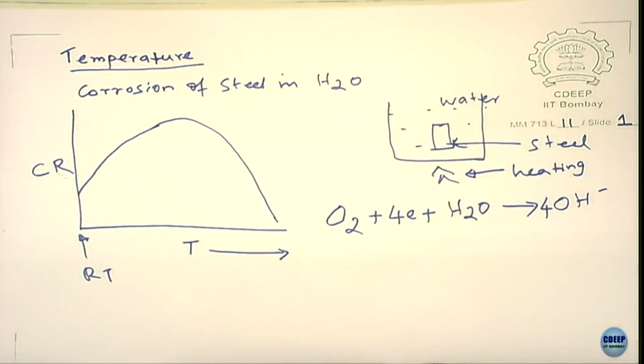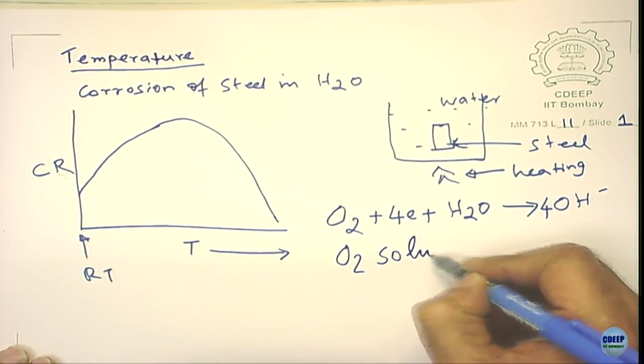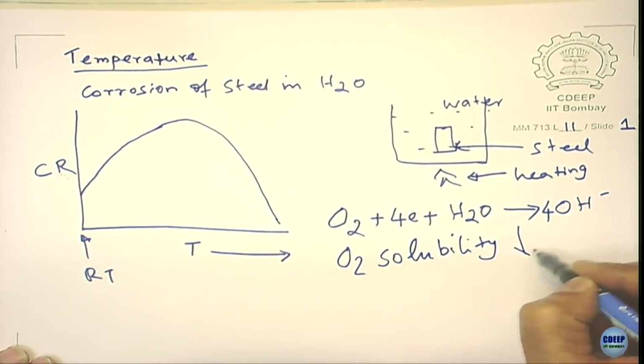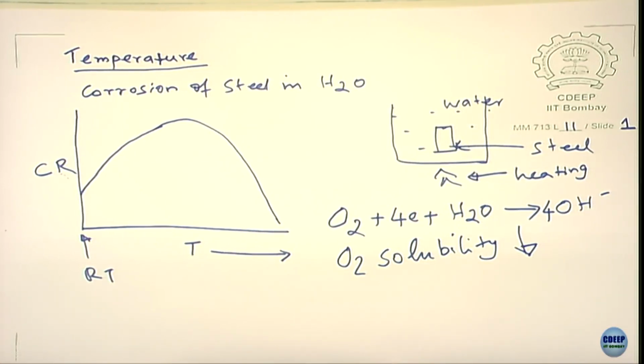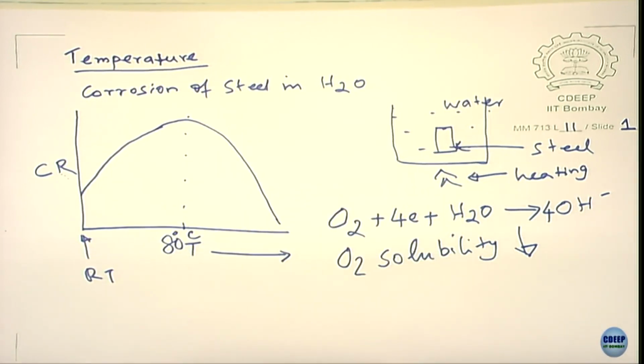Even when water vaporizes, what happens? The remaining water will have the same corrosion tendency unless you have some salts. You take pure water, you evaporate, the character of the water remains the same, right? It is oxygen solubility with respect to temperature that counts. So what happens when you raise the temperature? The solubility decreases, right? So there are two opposing processes. One, the rate of reaction is expected to increase with respect to temperature, but the oxygen solubility decreases. So the corrosion rate is decreasing. At approximately 80 degrees Celsius, you see that the corrosion rate drops significantly.